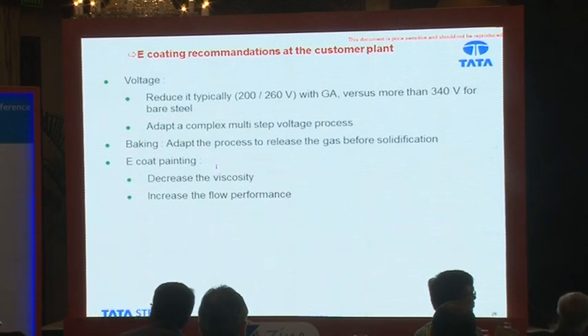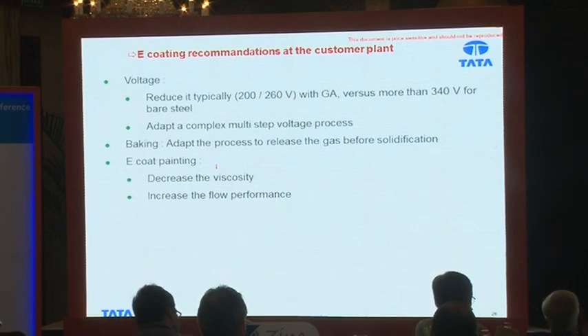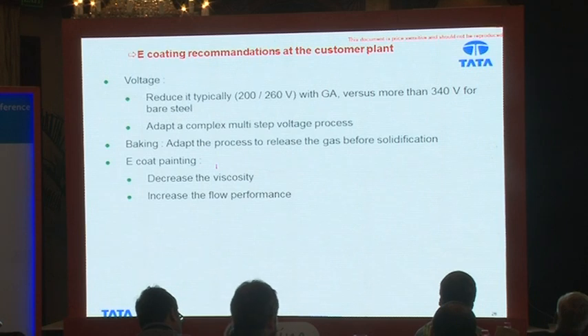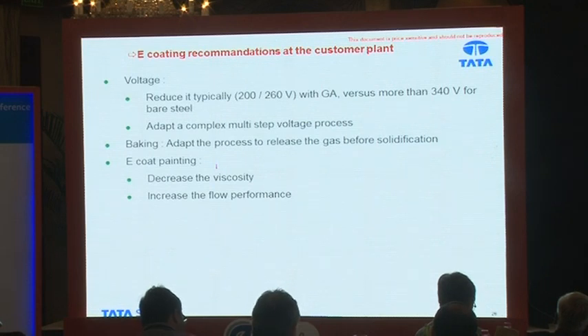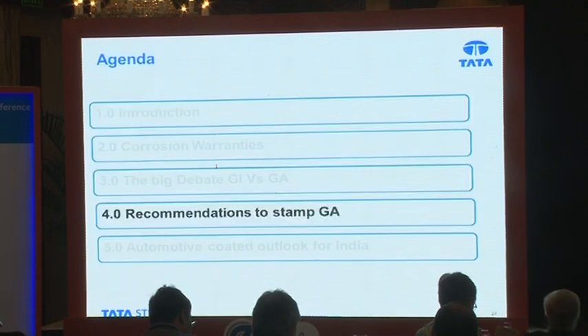There are other things which we tell the automakers: to decrease the viscosity of the ED paint and increase the flow performance. So all these shortcomings of GA have already been overcome. And if the automaker is using it for the first time, then as Tata Steel, we do give these recommendations to them, and we work very closely with them to get the right performance of the coated steels. There are certain recommendations also to stamp GA.